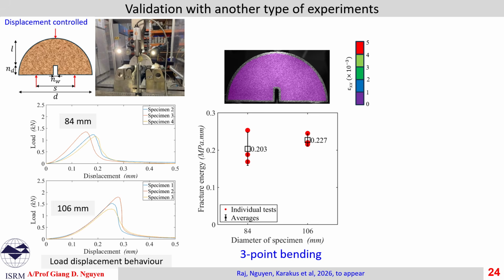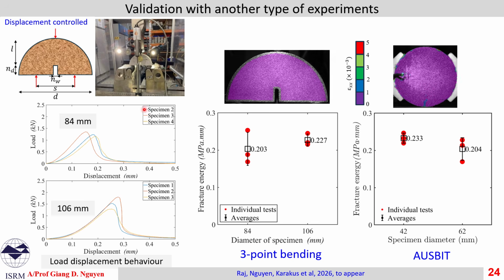Coming back to what we want, tensile strength and fracture energy. So tensile strength looks alright. Fracture energy, we need to validate it with other more acceptable methods. In this case, a 3-point bending test is used on 2 different types of specimen of different diameters, 84 and 106 millimeter. So this is a stable fracture process, and in the end, the load drops to almost 0.